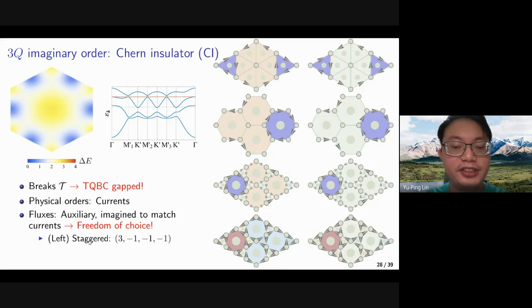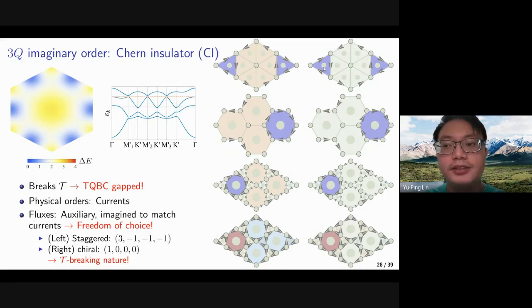The first choice is the staggered flux order, where we have the 3, -1, -1, -1 order. Meanwhile, we could also choose another kind of order, where we have penetration of flux only on the triangles, with all of the 3 edges being current induced. In this case, we have a 1Q flux order, and this kind of dilute magnetic field order could indicate clearly the time reversal symmetry breaking. That is, you can think of it as a Chern insulator induced by some dilute spontaneous magnetic field. And it is a kind of quantum anomalous Hall effect.